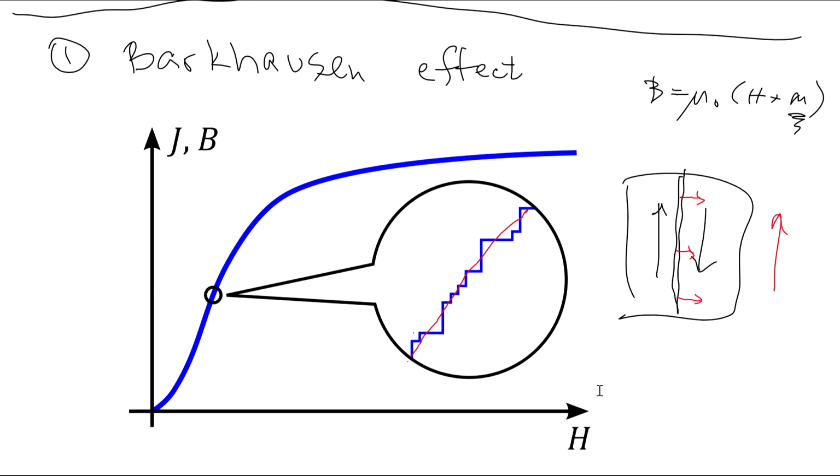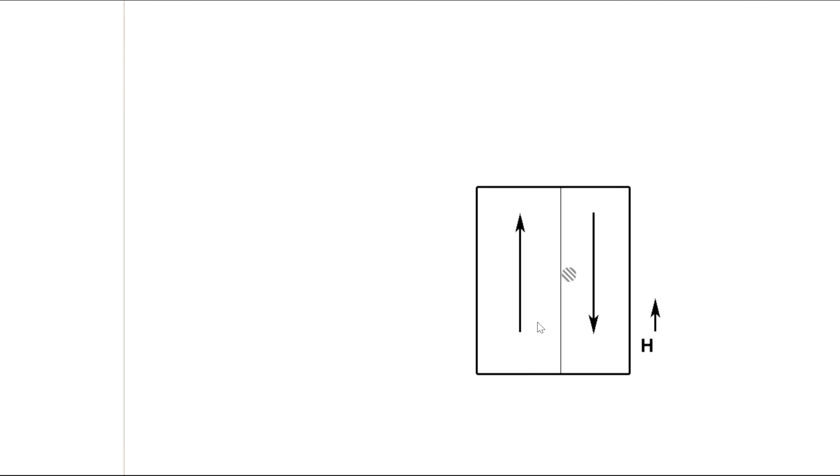So again, I will show you another. It doesn't show as a GIF, but I can show it here. Oh, let me do this. So you can see this is the domain wall. It moves through the impurity and pins. So it goes through the impurity and unpins suddenly. So these unpinning processes are responsible for the jumps, and you can see the magnetic field increases.